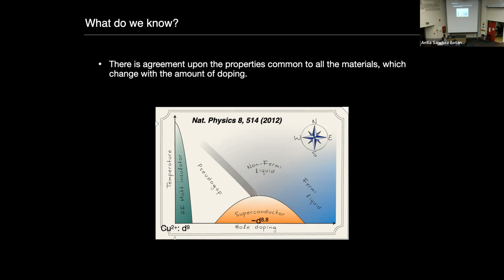So in the cuprates, we always start at the corner of the phase diagram, for which the parent material has coppers that are in a 2+ configuration or valence state, which means that it's a d9 ion to begin with, if you like. So for that filling, what we have always is an antiferromagnetic insulator. Then you start doping the material. At some point, superconductivity appears, keep on doping further, reach a maximum in TC in this dome, somewhere around 20% doping. That's this d8.8 filling. You keep on doping even further, and at some point, superconductivity just goes away, and we enter what is called the overdoped regime, where we should be finding a metal. That's, of course, a simplified view. There are plenty of other phases in this phase diagram, but for today's purposes, that should be enough.